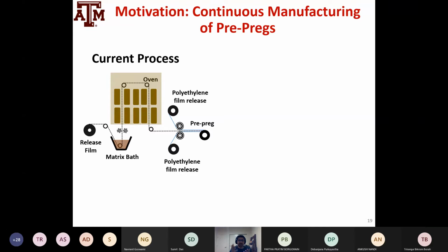When you make an aeroplane, you basically take these prepregs and you stack them up, and you consolidate and cook them. And that's what the Boeing company does. Before that, a company like Toray might make these prepregs. The way they make the prepregs right now is they have these carbon fibers, they dip them in a matrix, and they heat them in a large oven. Thermosets, when they start curing, start with, let's say, 0% cross-linking. Once they achieve 30 to 40% cross-linking in the oven, they're kind of not exactly bagged, but trapped between polyethylene films. And these films are later released, and you have the prepreg.